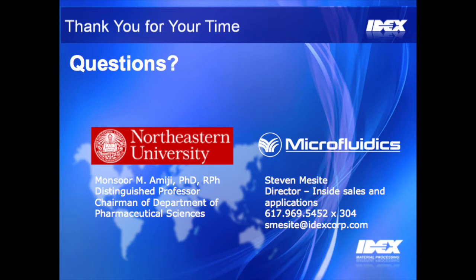Because the size, as I mentioned with our DALDA nano-emulsion, was around 100 nanometers. Same thing is true for the cyclosporine nano-emulsion. The size of the droplets is around 100 nanometers. So they're easily sterile filtered through 0.22 micron, and that allows us to create a sterile formulation at the end.